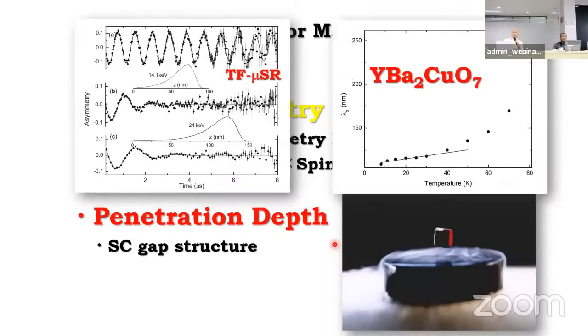And so this one, how to measure penetration depth. This is the YBCO type superconducting oxide. This one was a quite good result. How penetration depth is changing by changing the depth from the surface. So the surface point, the deeper point, the penetration depth is changing. This one is the first example to show such kind of interesting change of penetration depth.